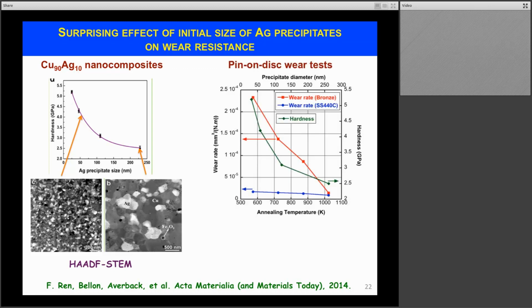But when we perform these wear tests, what we observed is that the wear response, which are the red and green curve here, varied as a function of the precipitate size, which you can read at the top, but in a way that goes against the prediction from Orowan's law. In particular, the precipitates that are the largest, here on the right side of this graph, are the ones that have the lowest wear rate. So the red and green curve reach the lowest value.